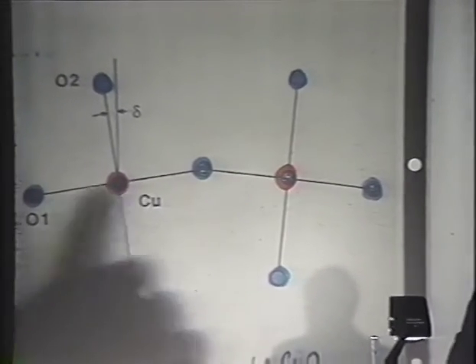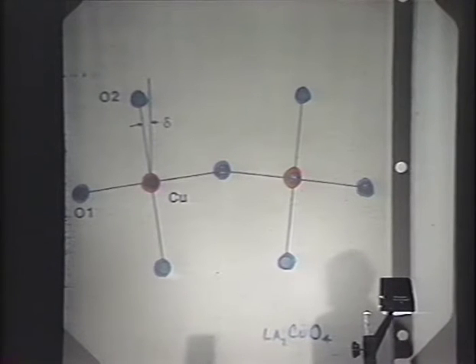It's a kind of transition that occurs in a number of perovskites. What it amounts to is going from a situation where you have chains of, in this case, oxygen, copper, oxygen, going forever in orthogonal directions, completely lined up, to the situation where you have these chains kinked at the oxygen. And when it's kinked, the material is extremely compressible, at least an order of magnitude more compressible than when these chains are not kinked, when everything's just pushing against itself.